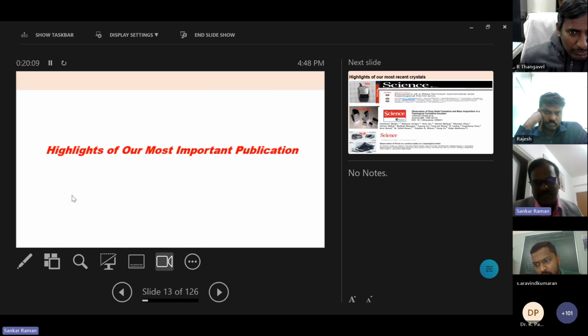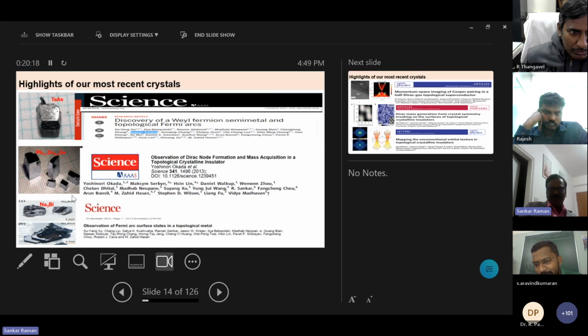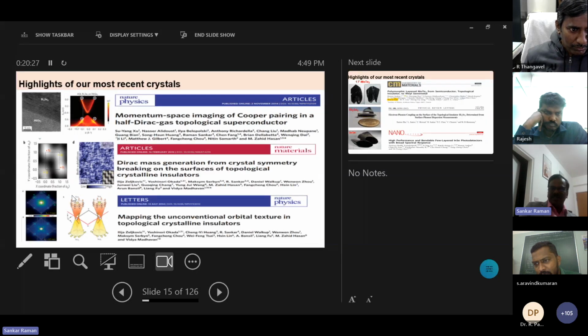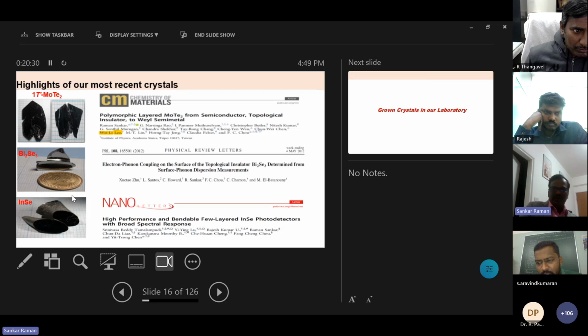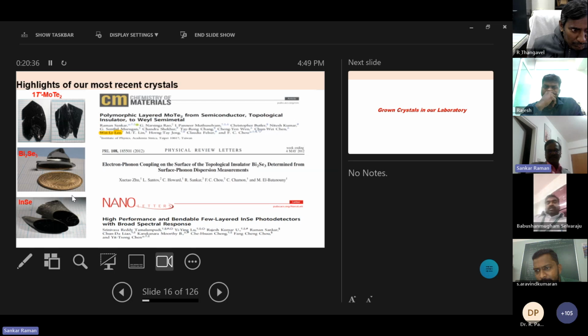Then some important highlights of our crystal growth: our lab has published a lot of papers. I'll just show you one or two percent of the papers here, because we are the first group to grow molybdenum ditelluride, bismuth selenide, and indium selenide. All were published in Science, Nature Physics, Nature Materials, and also Chemistry of Materials. One thing I need to inform you: for bismuth triselenide, we are the first group to grow exactly stoichiometric crystals, because most groups grow it but have mostly selenium vacancies. If you have a selenium vacancy, you cannot exactly point out the topological nodal line band gap.